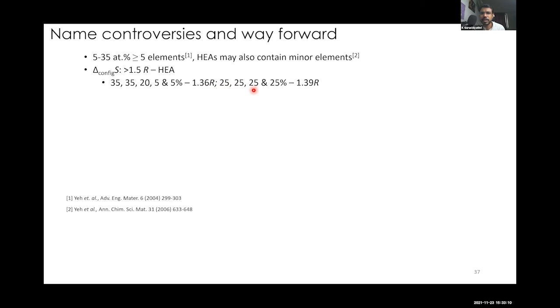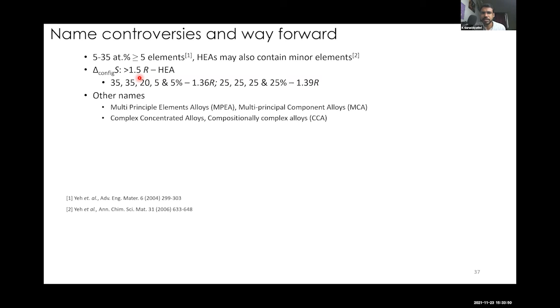On the other hand, look at this alloy, 25, 25, 25, 25. Only 4 elements, and the configurational entropy is higher than in this case. So can we have only 4 elements and still call it a high entropy alloy? Because this configurational entropy is higher than this case. So these two kinds of definitions are not strict definitions. They're broad guidelines only. Okay, so you don't need to take it very seriously, but you should try to stick to these things. Don't deviate too much from this when you are designing a high entropy alloy. So people came up with other names: multi-principal element alloys, multi-principal component alloys, complex concentrated alloys, compositionally complex alloys, because we are not bothered about stabilizing a single phase anymore.